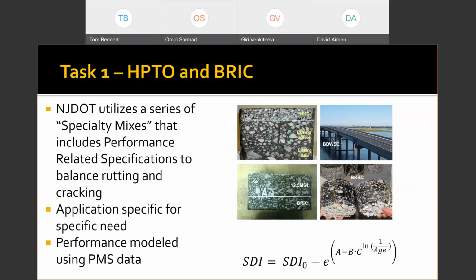For example, over here on the left, we have what we call an HPTO, which is a high performance thin overlay. That's a pavement preservation type of material, goes down 1 inch or less, but adds a significant improvement in structure, flexibility, and durability over the pavement while sealing it. So it's a very good mix, and again, requires the use of performance testing to make sure that it's both rut resistant and crack resistant. We have a bridge deck waterproof surface course mix. The intent is, again, to preserve our bridges. The benefit of this material is that you don't need an underlying waterproof membrane. This acts as that on its own. And also because it's placed at about 1 inch thick, you can typically reduce the dead load weight of bridges by about 50% if you're going to use an asphalt overlay.